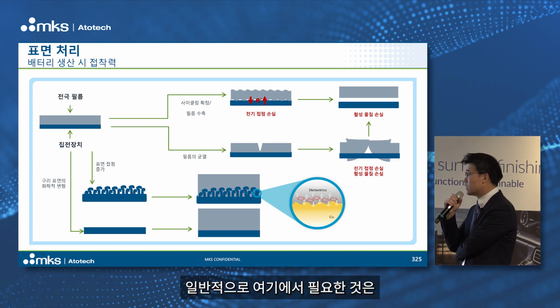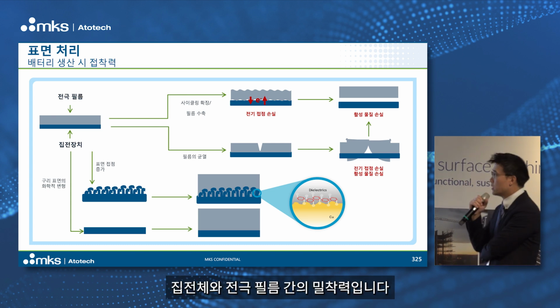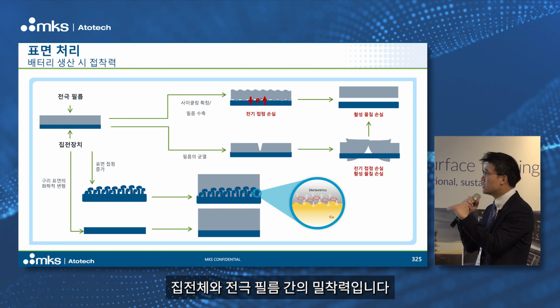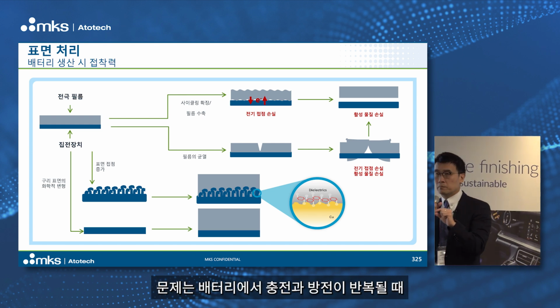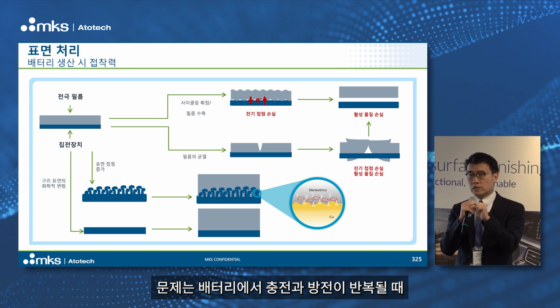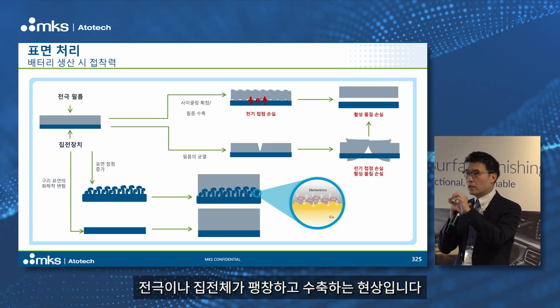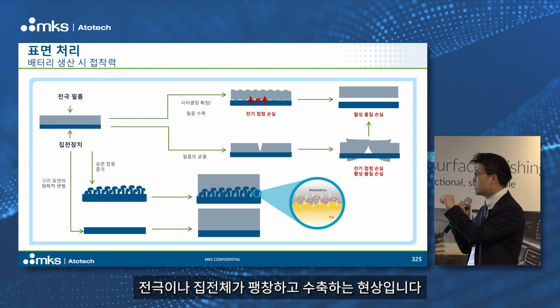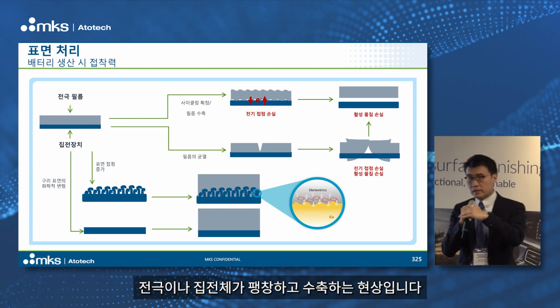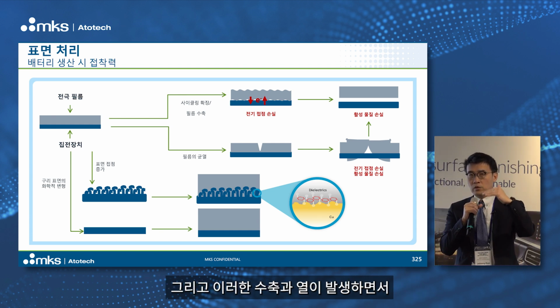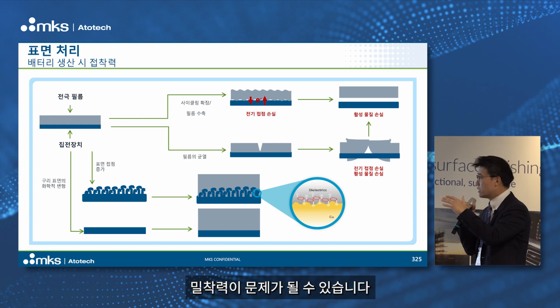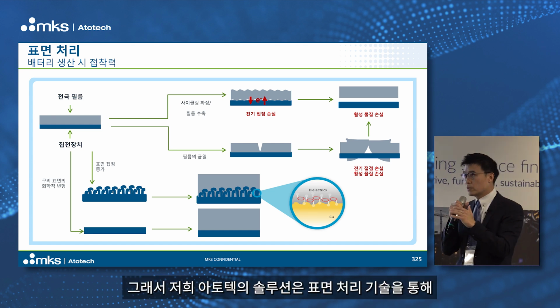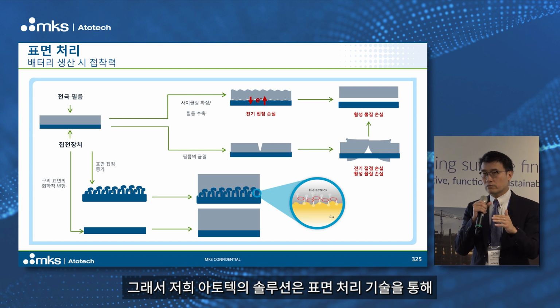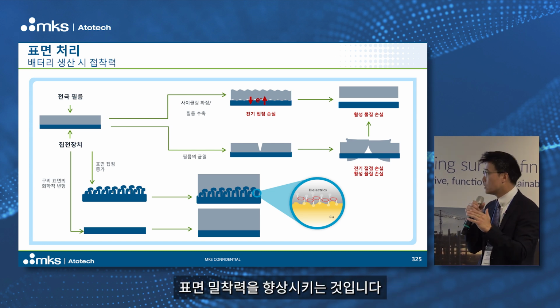Next one, I think this is an example of another current collector, which is aluminum. And normally the need here is the adhesion between the current collector and the electrode film. The problem is that after charging, discharging in the battery, the electrode or even the current collector is expanding and also contracting. And normally with all this contraction and heat, the adhesion could have some problem.